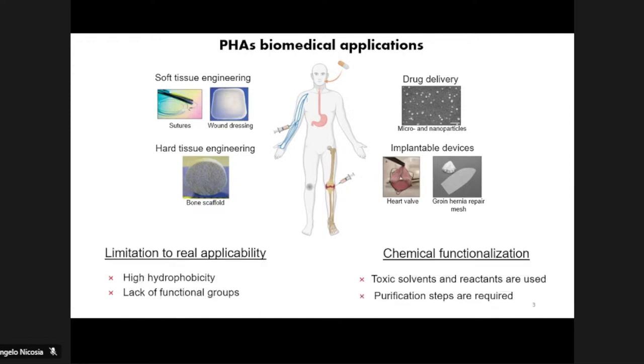However, the high hydrophobicity and the lack of functional groups could limit their stability in physiological conditions and therefore their real applicability. For this reason, chemical modifications of PHAs are needed to tune their hydrophobicity and make such materials a valuable alternative to synthetic polymers. Unfortunately, toxic solvents and reactants are used for polymer functionalization, resulting in several purification steps and in the loss of the advantage of using a biomaterial.